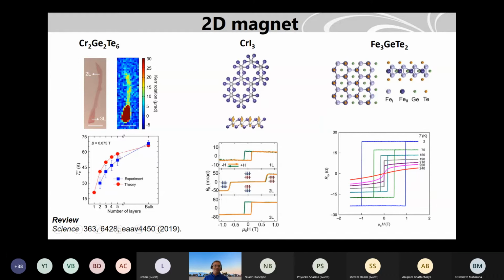So once you go to monolayer, the TC is very low, and for multi-layer, it's higher. So this is an insulating 2D magnet. And chromium iodide is actually also a 2D magnet in monolayer. But when you go to multi-layer, it's actually an antiferromagnet. Okay, so they couple antiferromagnetically.